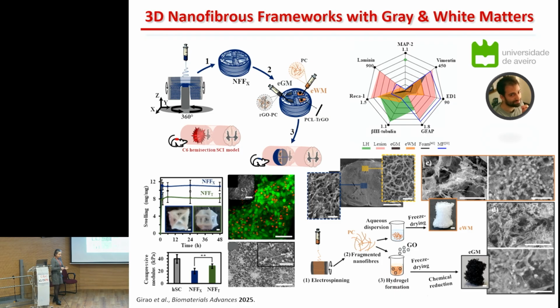We moved to the in vivo and we did a comparison of the results with our foams and our microfibers. The response of the different components are here much better than the injury group. You see this pink color, the different response for the different parameters that we evaluated, the markers, but it's still not better than the scaffold. The reduced graphene oxide that was simple, just a sponge, 3D porous, highly porous response, so we stopped the work in here.